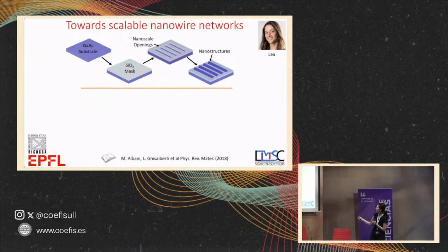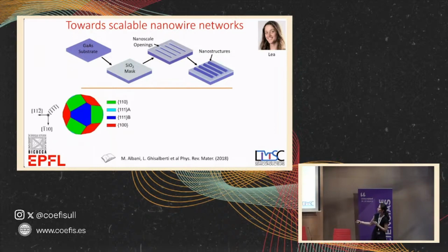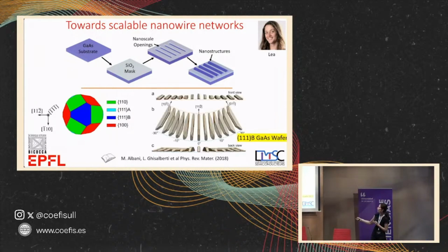So we do this, and we learn what the crystal wants to do, because there's crystal facets, there's crystallography, and you cannot just make a round shape, because as you've seen in the geological museums, the crystals want to have several facets that are very well determined. So we look at what these facets would be for gallium arsenide, and these are the facets that have the lowest energy. And so when you have the orientation of the substrate and the openings, if you make slits in all these directions, you will have only few that have vertical facets and that are a single crystal, not have defects.